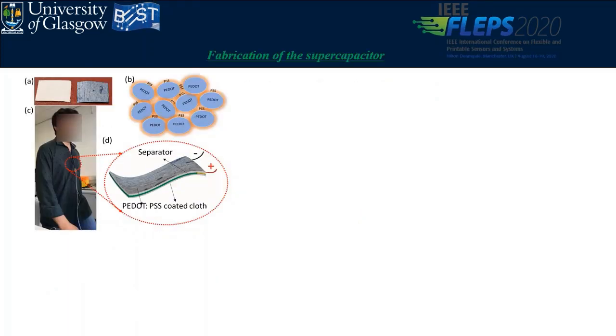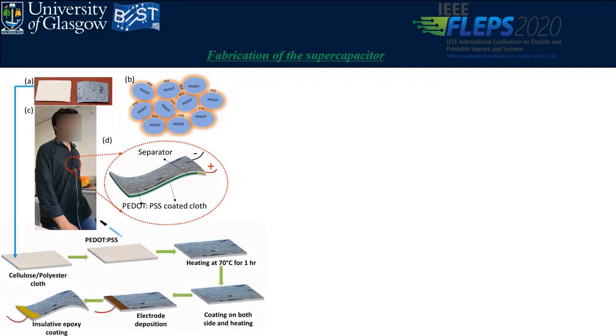And here you can see how we fabricated the devices. Here we have a cellulose polyester cloth, and then we coated it with PEDOT:PSS. This PEDOT:PSS is modified with DMSO, dimethyl sulfoxide, to enhance the conductivity. Initially we compared the performance of pure PEDOT:PSS and the DMSO-modified one, and I'm going to discuss the performance in later slides.